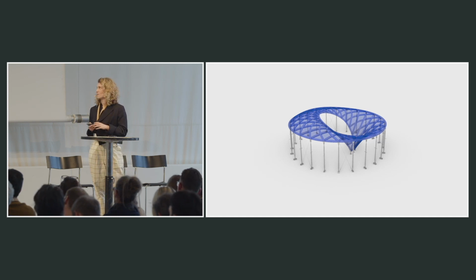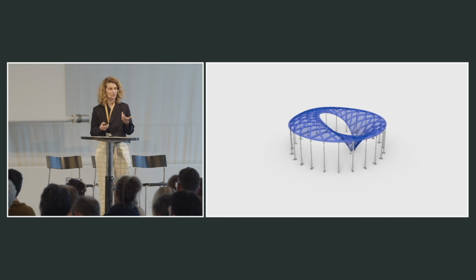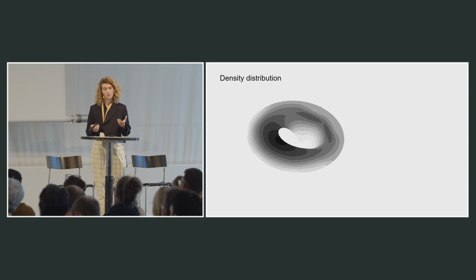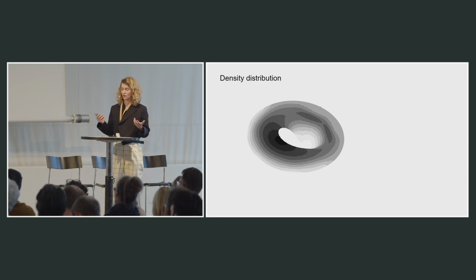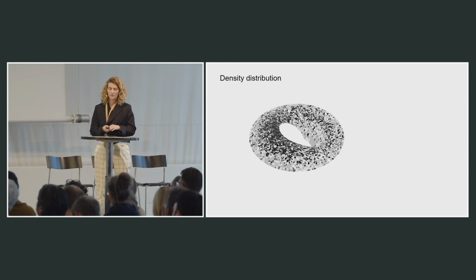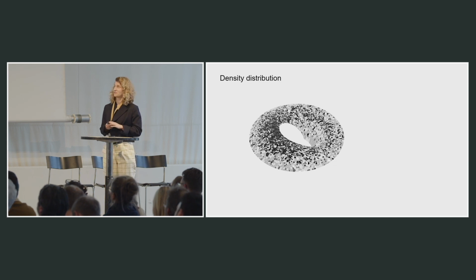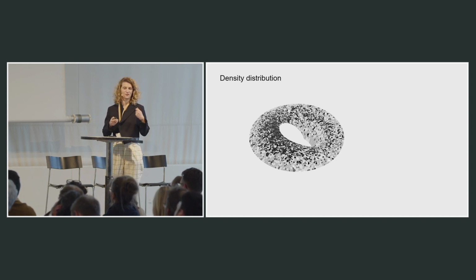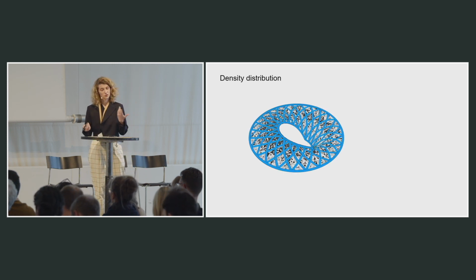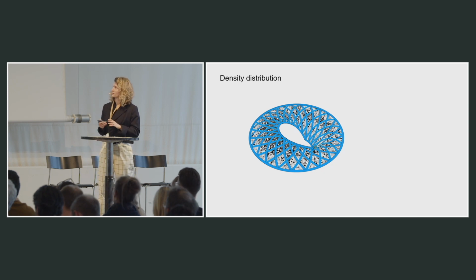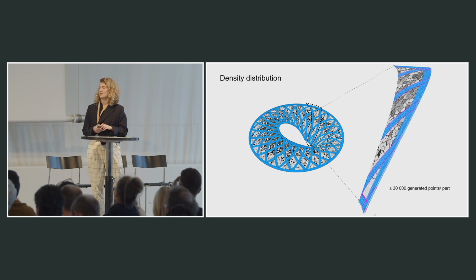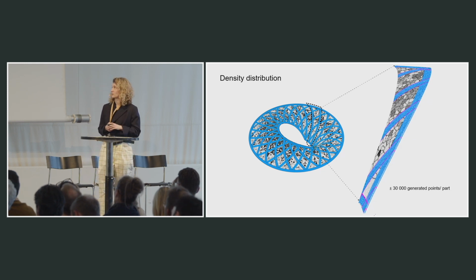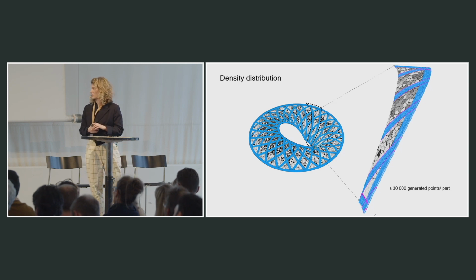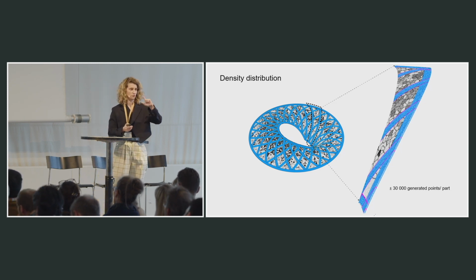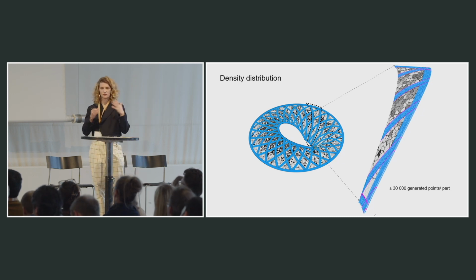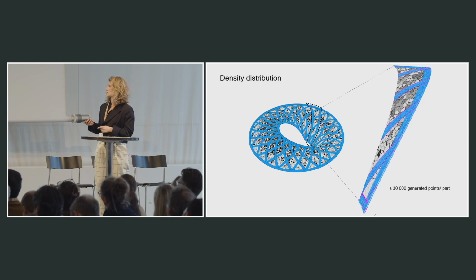To decide on the density or the porosity of our membrane and the expression of it, what we did is we started with a density distribution of where we wanted to have a more closed and more opened expression, and divided that into different zones that would then control the amount of openings that we use on that particular side. That was also superimposed on the ribs that you see there, and for each one of the parts, a knitting pattern is generated on a 3D surface, which entails the generation of about 30,000 points for each one of those strips. So having 74 strips gives you the idea of the magnitude of the computational step that needs to be done in this case.